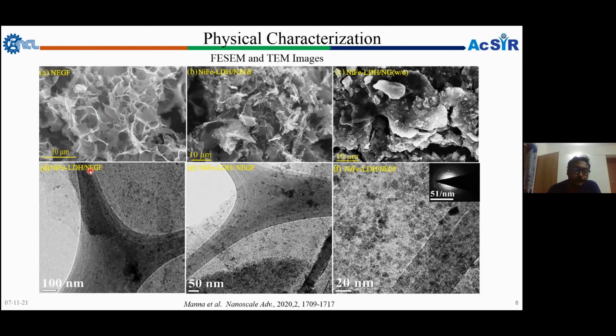This is for the 3D structure formation characterization. Further, the TEM image also suggested that the nickel iron layered double hydroxide particles are uniformly distributed, and the particle sizes are very small. In the further high magnified image you can also see that the particles are homogeneously distributed, and inside here you can see the selected area electron diffraction. Here the bright spots are formed, and they are systematically distributed, because of the crystalline structure of the nickel iron layered double hydroxide.